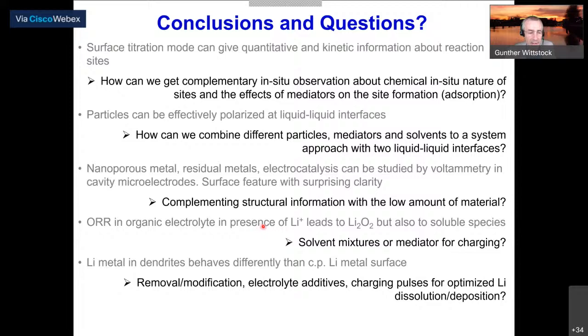Oxygen reduction reaction in organic electrolytes in the presence of lithium plus leads to lithium peroxide, but also to other soluble species. And the question is whether solvent mixtures, mediators, or other additives can drive the product spectrum of that reaction to maybe form less of these soluble products and direct the deposition reaction a certain way. We're working on that now.